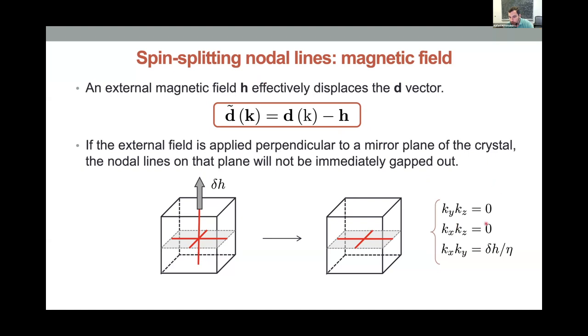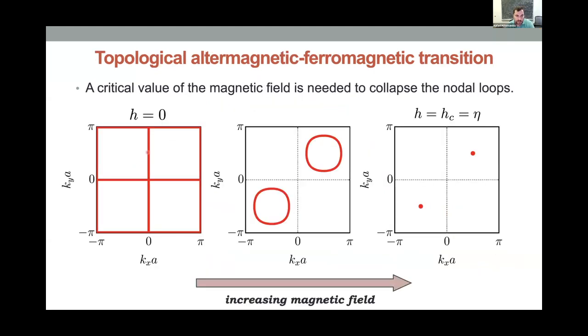And what you find here is that the nodal lines still have one set of nodal lines. And instead of being vertical or straight lines, they're going to be parabola. In fact, you can show this exactly playing with this model: the moment you start applying a magnetic field, these nodal lines detach from these high symmetry directions, but they're still present. And that's because they still have one mirror to protect them.